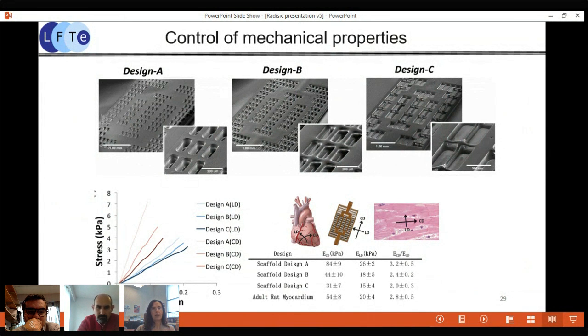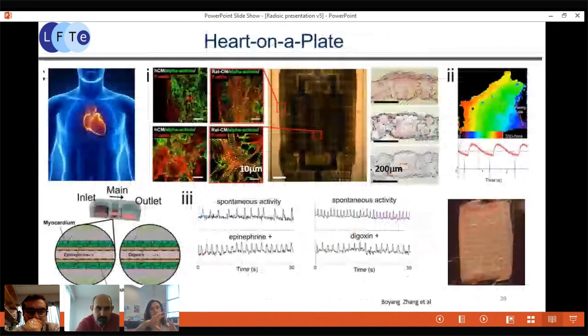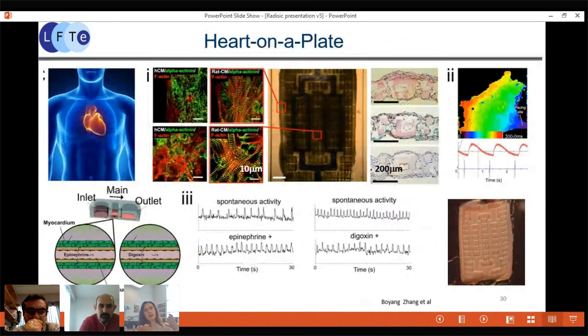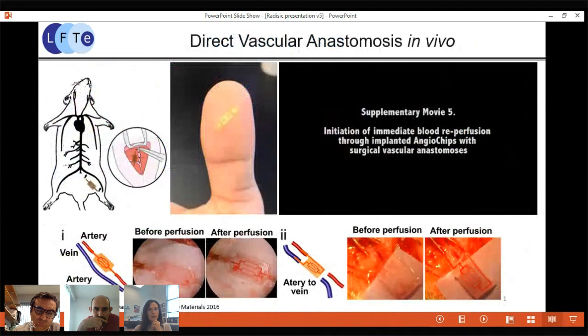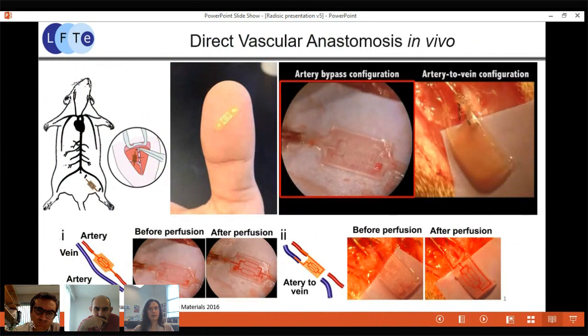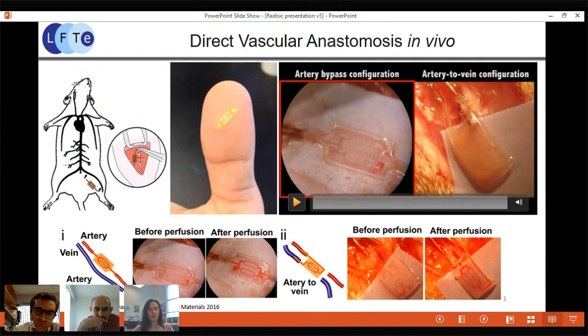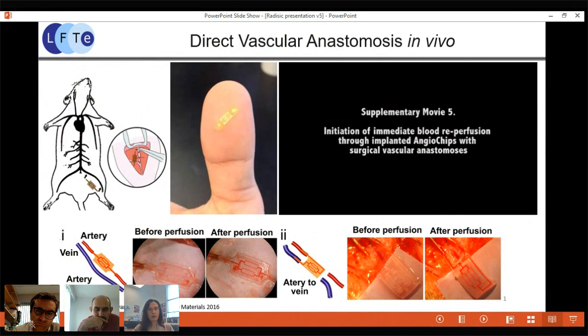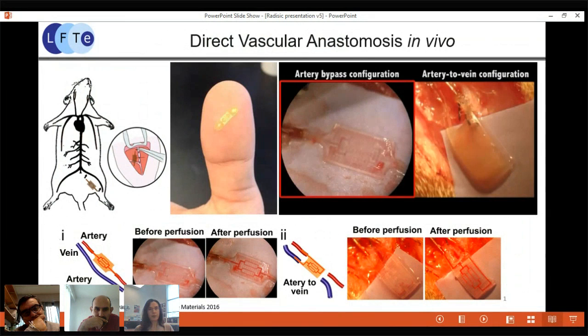Once you seed the cells, they will go all around the scaffold struts, and all of the pores in the scaffold are interconnected in the Z direction. And this now enables us to create a tissue that twitches and that propagates electrical impulses. In addition to that, we can implant this tissue by direct anastomosis. You can see the inlet and outlet here. And we'll just hopefully let that move around. And we can establish flow immediately.